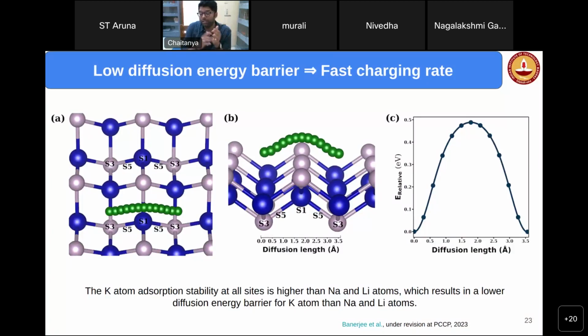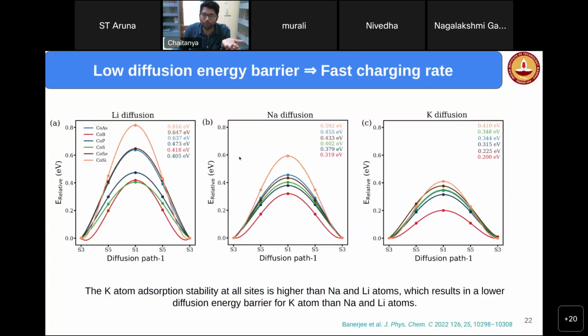Okay. So now we understood that among these various anti-MXene surfaces, lithium, sodium and potassium are there. Potassium is able to easily diffuse on the surface, but lithium and sodium are also reasonably okay. They have only 0.6 or 0.8 electron volt migration energy barrier, and all of them are adsorbing strongly. All of them are good electronic conductors. So till here, whatever we have discussed is with one metal atom on the surface. Now, when we are considering the real battery, as you know, when you are, for example, charging or discharging, a lot of metal atoms will be involved. So this is what we are trying to understand next. How many metal atoms can this particular material actually absorb? We worried till now only about one particular metal atom.